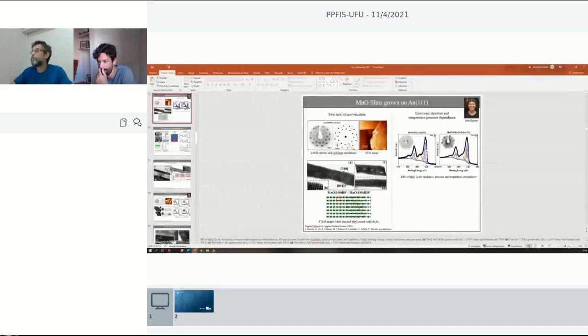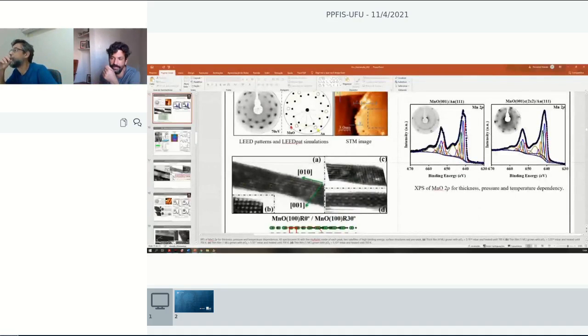And then what we do is we profit from the literature, of course. We do the fitting, so Jade, Astrid, all my students do that. The packages don't come with the system, so you have to pay for them. One very well-known package is CasaXPS, which we use because it came with the system that we ordered. In the literature, people also use Igor Pro a lot because you can use the Voigt functions. CasaXPS is a common package, and XPS Peak Fitting is another software that you can find that is free, like Igor. And then you use some routines to decide, for instance, we have a manuscript exactly discussing that. But let's see this example here.